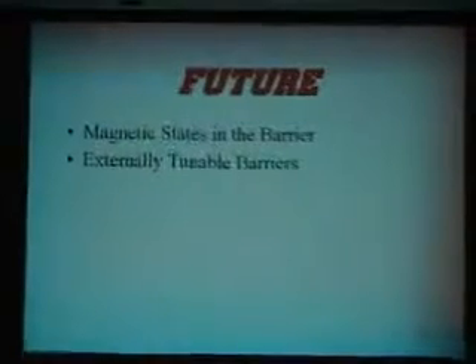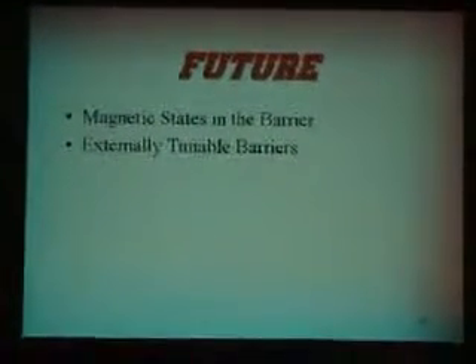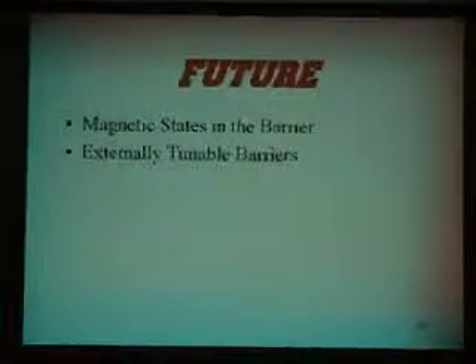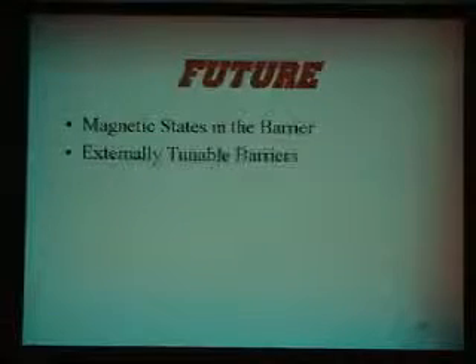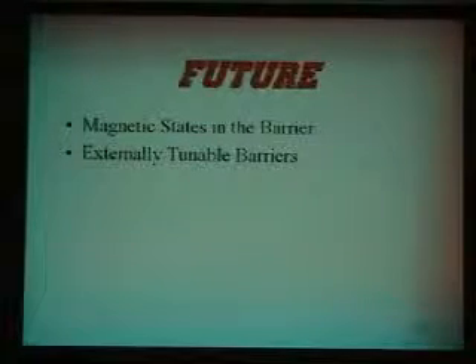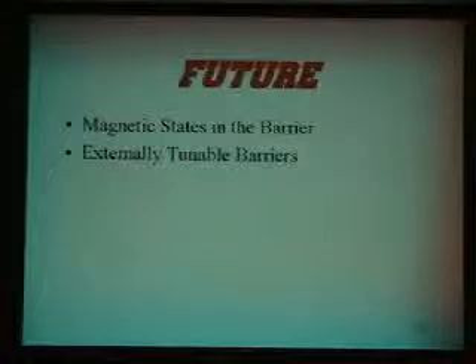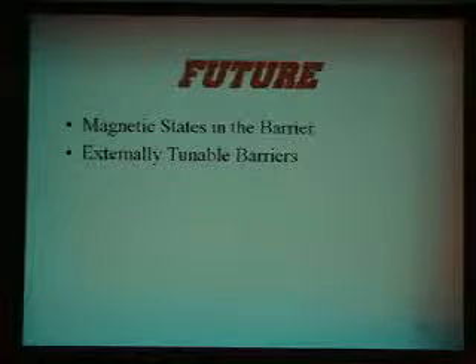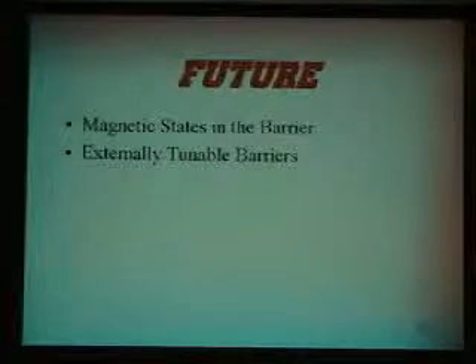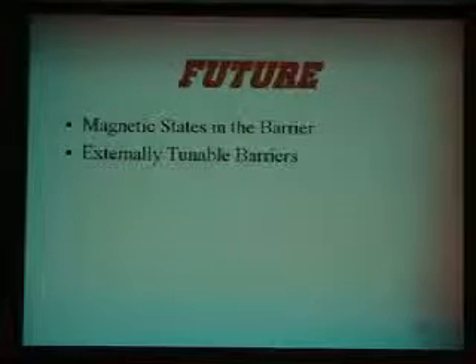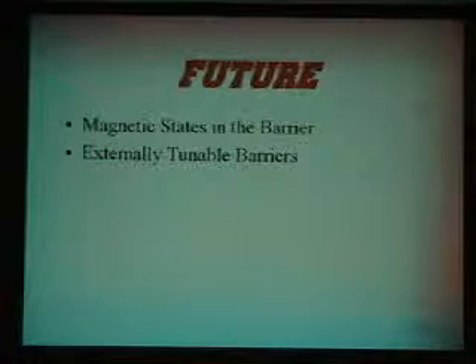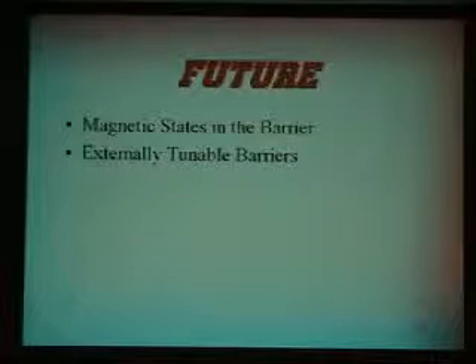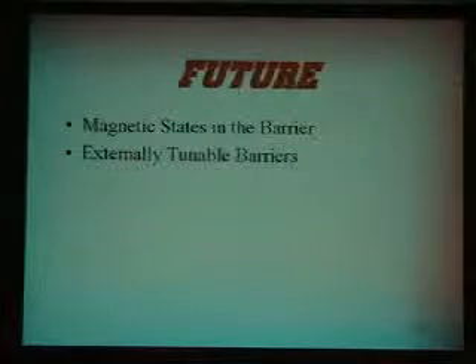You can think of a barrier that you stick in there that you can actually tune externally. What I mean by that is you can change the barrier height externally, and there are ways of doing that. One way is to use materials like transition metal oxides that have huge changes of resistivity with all kinds of stimuli, magnetic fields or light. So you can change the barrier height and make tunable tunneling.